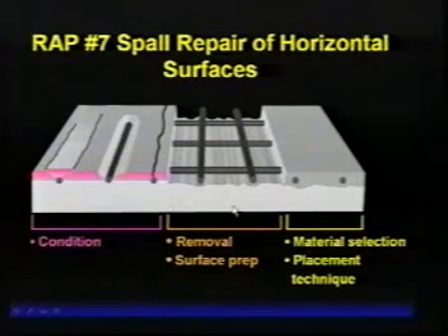The last technique, which the first two I talked about were form techniques, the form and pour technique and the form and pump technique. The difference between, just revisiting that, the form and pour was basically gravity feed behind formwork, and the only pressure head was the liquid head of the material, versus the form and pump technique, which is you're actually adding pressure from the pump line. So you have the existing head from the material plus the pump line pressure up to 14 psi.